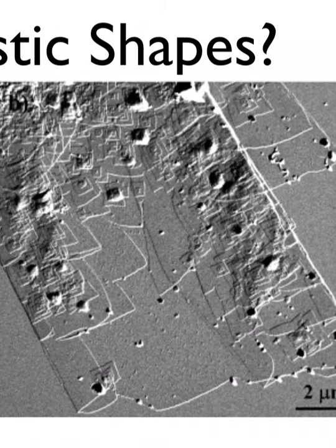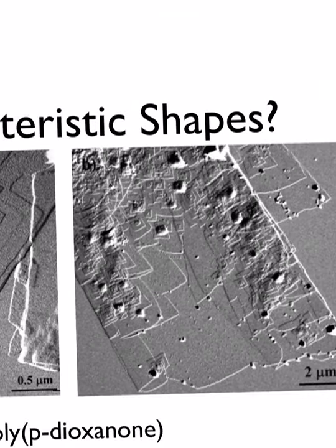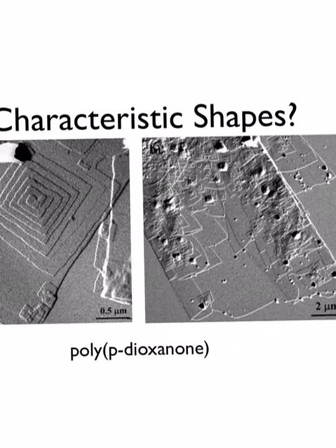And so this is one of the reasons why it's so hard to see single crystals in melt crystallized plastics, because this is considered big. Without barriers to polymer motion, you throw in a melt structure which is just surrounded by polymer chains, and crystallization is very limited. And so we get these very small nanometer-sized crystals that we more or less just recently have the ability to actually see. And so this was an important discovery for them because they couldn't really see these things in the melt.